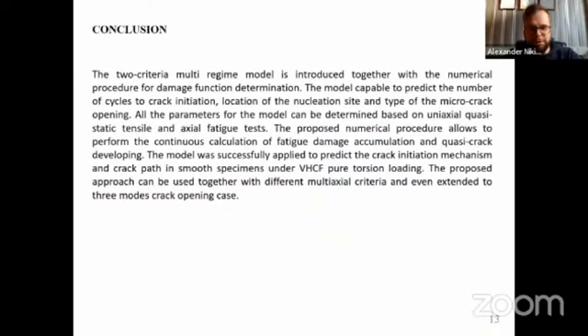So finally, we arrive at the conclusion. I can say that we observe two types of crack, surface and subsurface, and we introduce a model based on damage theory. Applying this theory, we are capable of predicting some special features of crack initiation under very high cycle fatigue. That's all, I think.